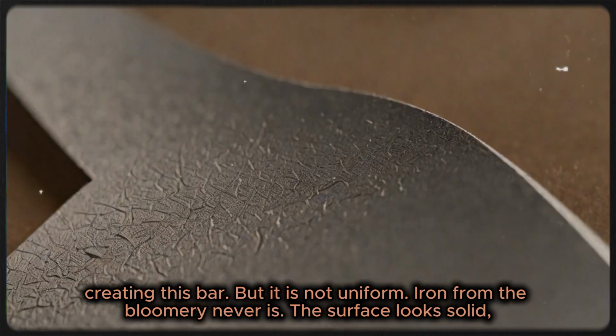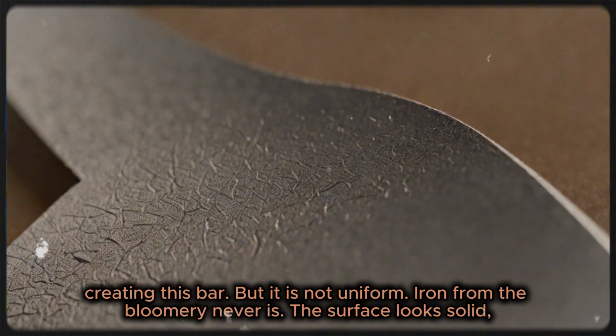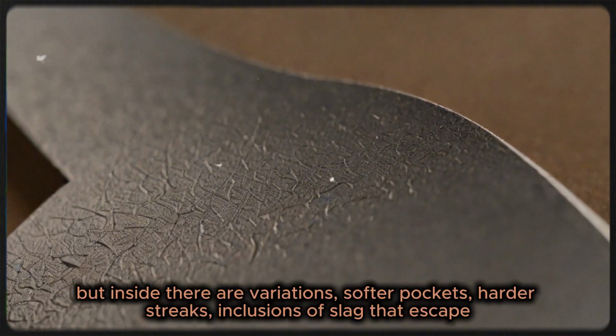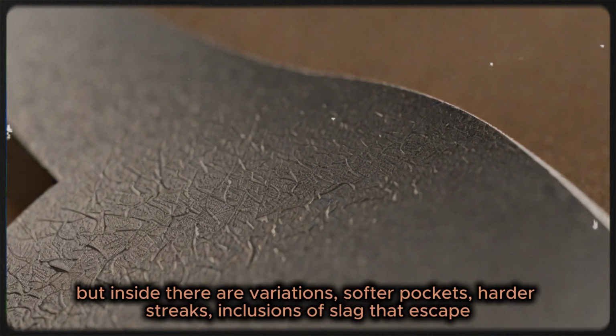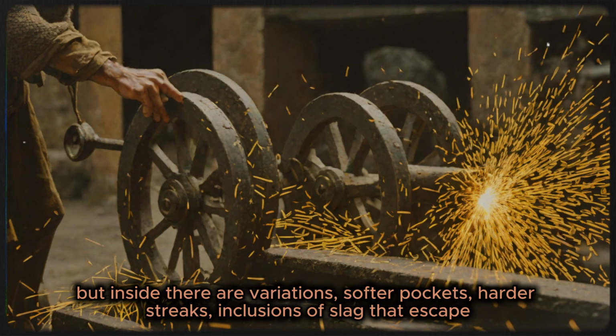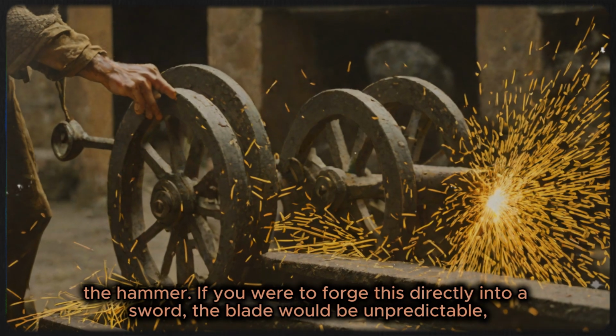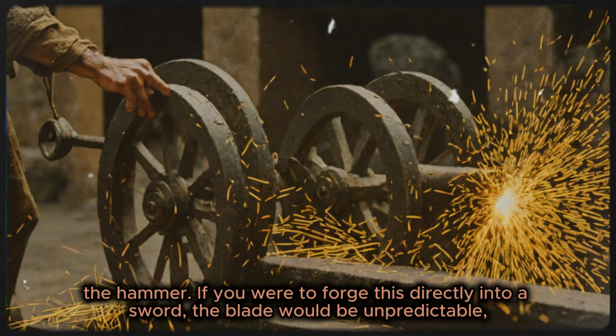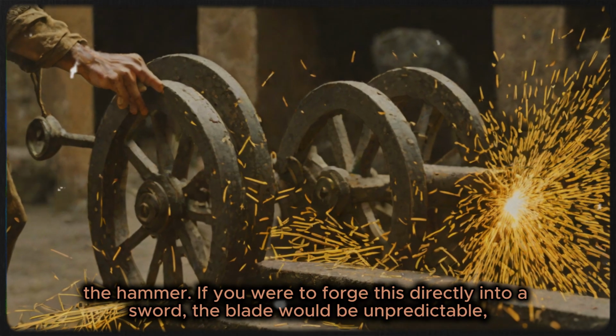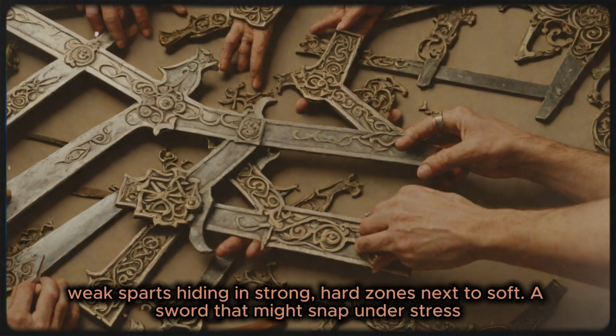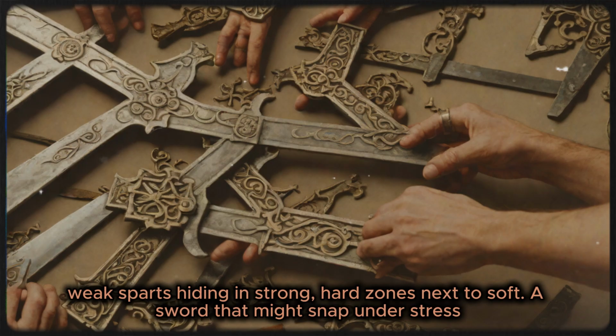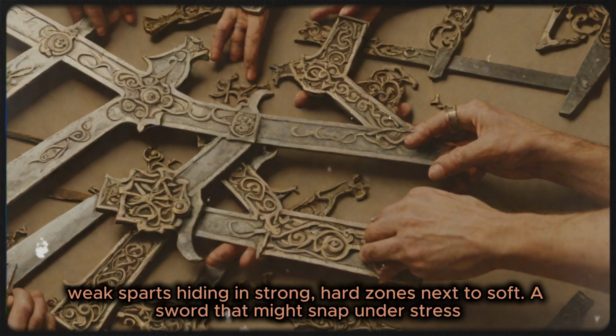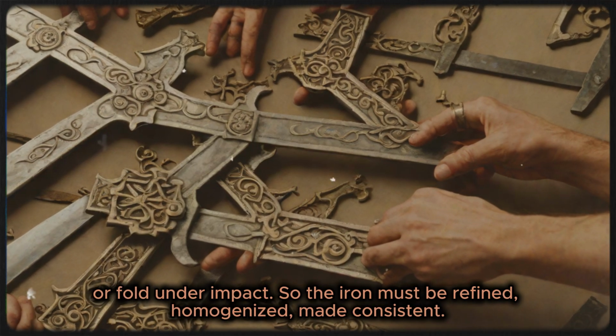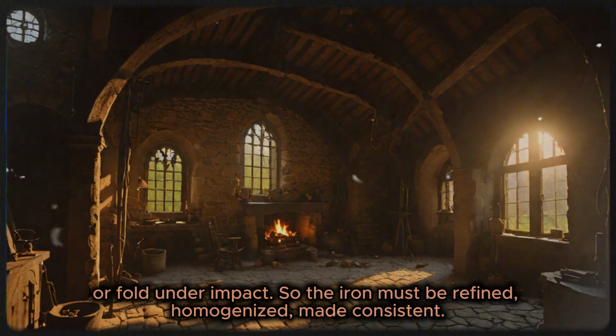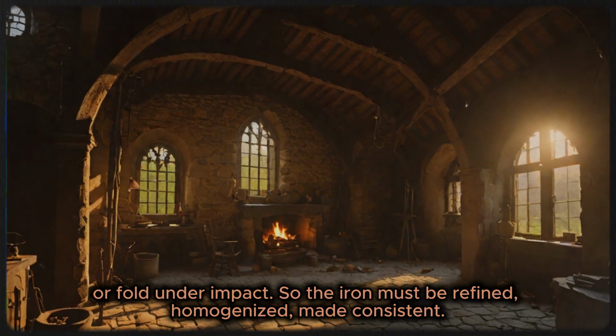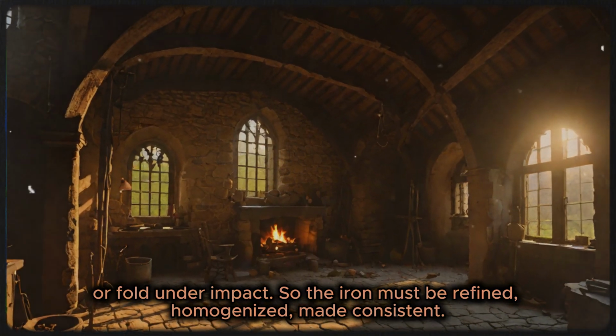But it is not uniform. Iron from the bloomery never is. The surface looks solid, but inside there are variations, softer pockets, harder streaks, inclusions of slag that escape the hammer. If you were to forge this directly into a sword, the blade would be unpredictable, weak spots hiding in strong, hard zones next to soft. A sword that might snap under stress or fold under impact. So the iron must be refined, homogenized, made consistent.